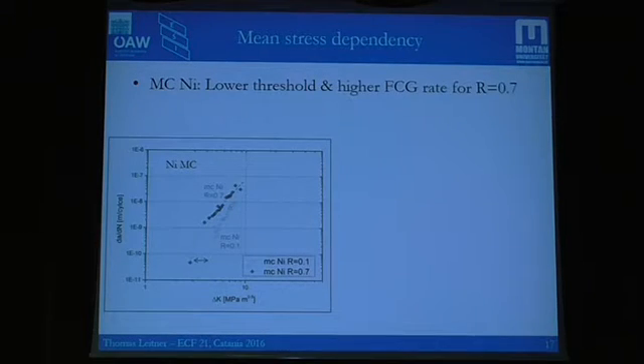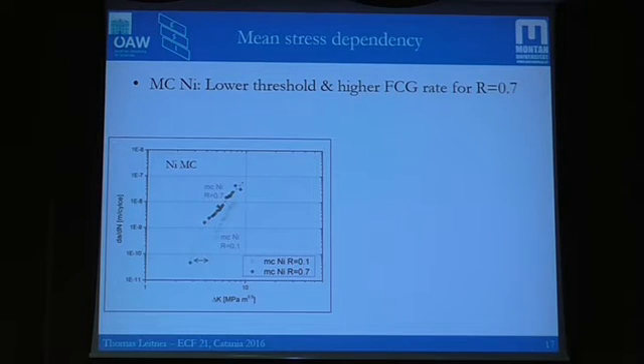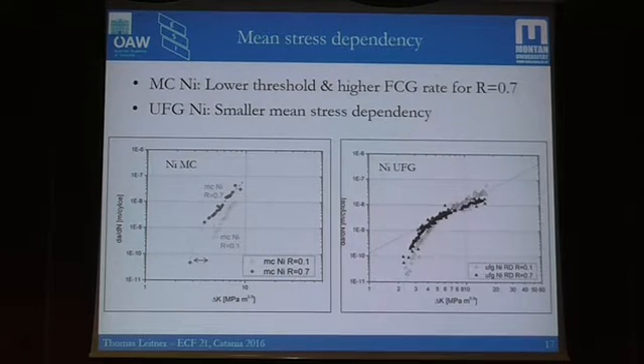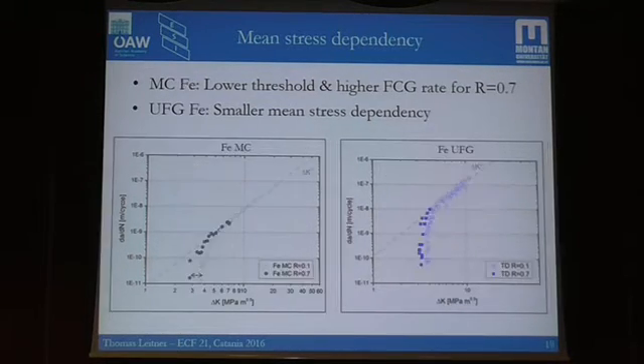So let's come to another interesting topic for these ultrafine grained metals, the mean stress dependency. What we usually see in our microcrystalline microstructures is this mean stress dependency, that we have a lower threshold and higher fatigue crack growth rate for higher mean stresses, like shown here. At lower R ratios, we get higher threshold values and slower fatigue crack growth. So there's quite a difference. When we have a look at our ultrafine grained nickel, we see that we have a much smaller mean stress dependency. The same is also true for iron, where we see the same tendency of a smaller mean stress dependency in our ultrafine grained microstructure.